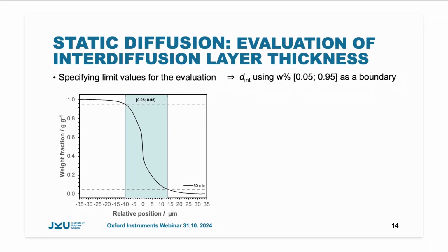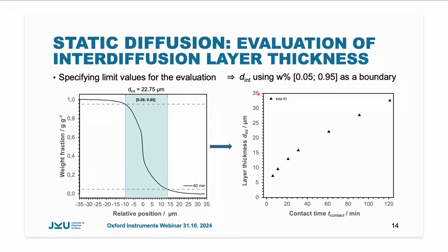Therefore, we would like to evaluate the interdiffusion layer in a little bit more detail. And for this, we have to specify limiting values for the evaluation. Because if you look at the individual interdiffusion layer profile, you see that there's a very smooth transition from the pure polymer to the interdiffusion layer. We just decided to use boundaries of 5% and 95% for the evaluation to get the interdiffusion layer thickness for all of the samples. And now we can plot the interdiffusion layer thickness, which is correlated to a weight fraction, against the contact times. And we see a nice smooth increase of the curve.